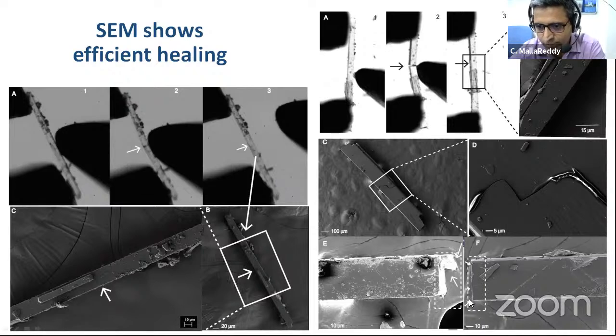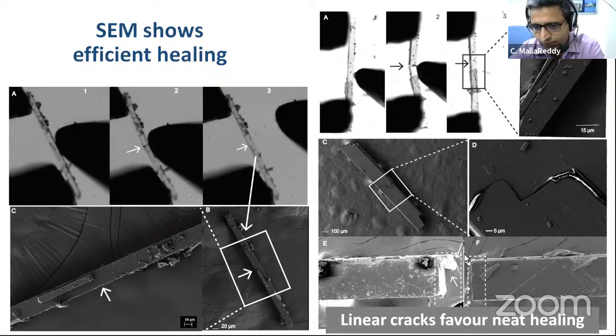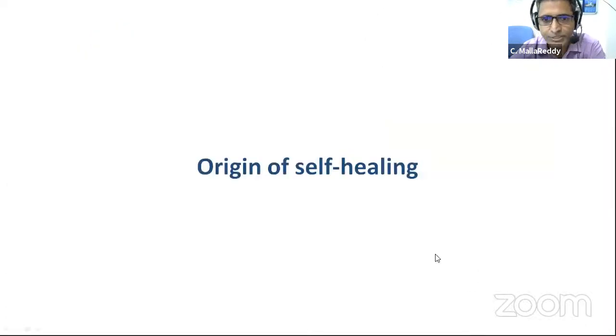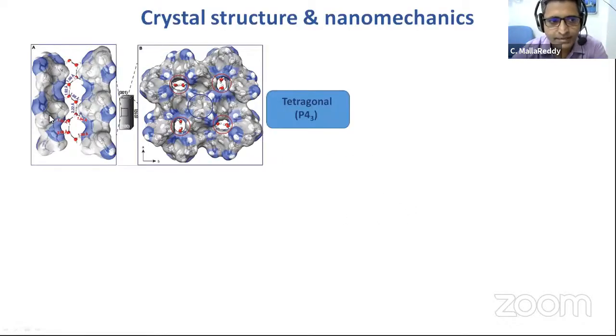Wherever you have a good healing, we mostly saw a very nice linear crack without any debris in between. So in those cases, the healing is very, very efficient. So what is the origin of self-healing? We wanted to understand. Then we looked at the crystal structure.